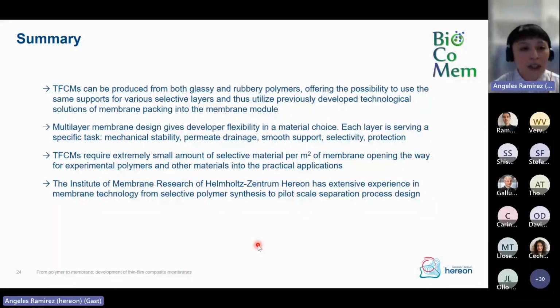Now, this multi-layer membrane design also offers us flexibility in the choice of a given material. And also a very important thing is that the fabrication of such membranes requires a very small amount of selective material per square meter, so around 100 milligrams of polymer for 23 square meters of membrane, for example. So this opens the way for experimental polymers to be used and tested for real applications.